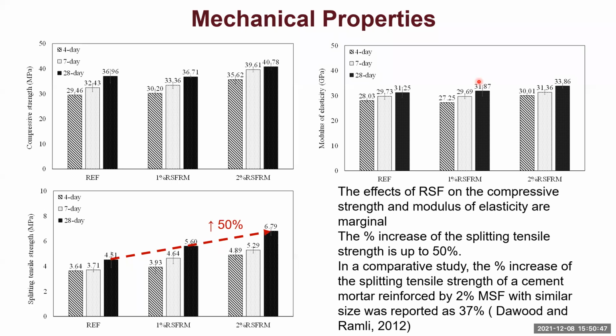Here I'm showing some mechanical properties results. The major finding is that adding those recycled steel fiber did not significantly change the compressive strength and the modulus of elasticity. However, the split tensile strength of the cement mortar was improved significantly. Here, as you can see, by adding 2% recycled steel fiber, the split tensile strength was improved by 50% at 28 days.